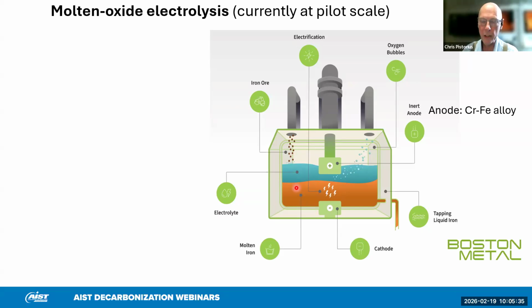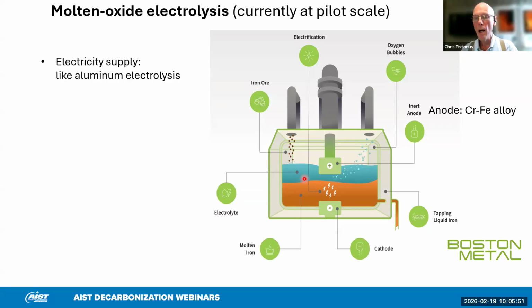The crucial part of this technology is the inert anode, which, at least in the published documents, is a high chromium with a bit of iron alloy, which has really unusual properties to help it withstand the conditions. And that's really, of course, the innovative part of the process, and the only part that doesn't strongly rely on existing technology. The electricity supply will be like aluminum electrolysis. The refining after tapping will be normal ladle metallurgy, well established.